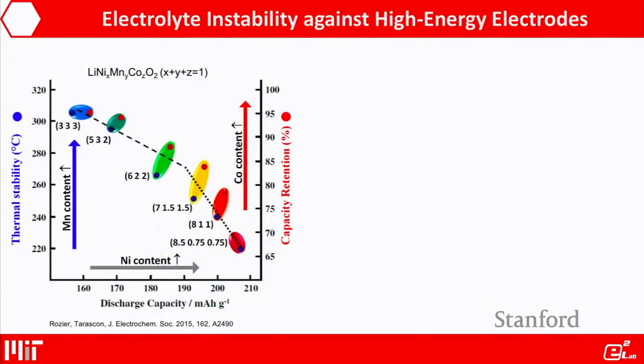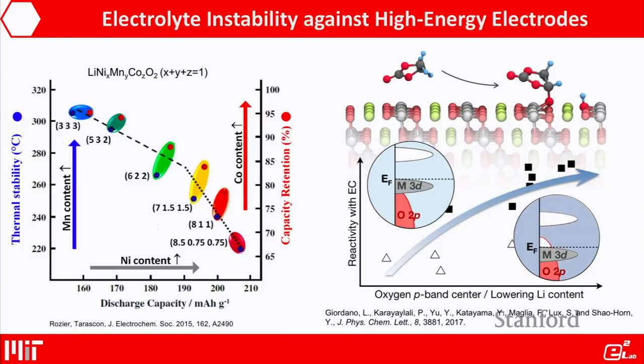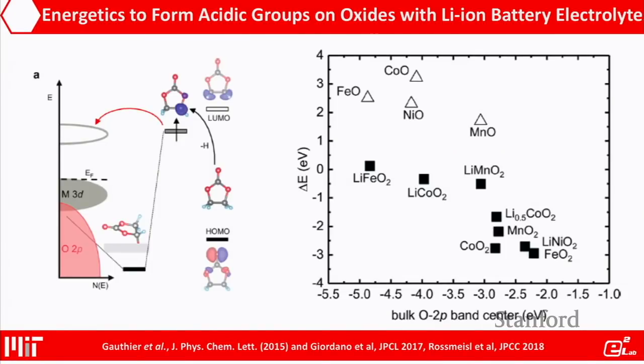I want to draw a connection between what we do in catalysis, which is playing with the electronic structure of metal oxides and changing the energetics of metal oxides and oxygen, to lithium-ion batteries. In lithium-ion batteries, we have similar metal oxides, except here we are looking at lithium-containing metal oxides next to an organic electrolyte, let's say EC or EMC. And we find there's an interesting correlation with the covalency of these oxides as well.